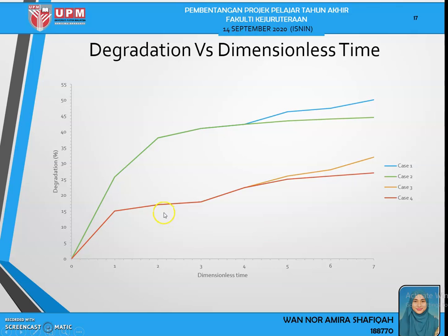So this is the graph of the case study. Based on these figures, the effect of diffusion and precipitation velocity parameters can be understood in these models. It indicates that a quick precipitation velocity results in the formation of a hydroxyapatite layer even when the diffusion is low. The slow dissolution rate slows down the precipitation phenomena because the surrounding SBF does not obtain any released ions. So if we can see here, the degradation increases with time, even for the 4 cases.